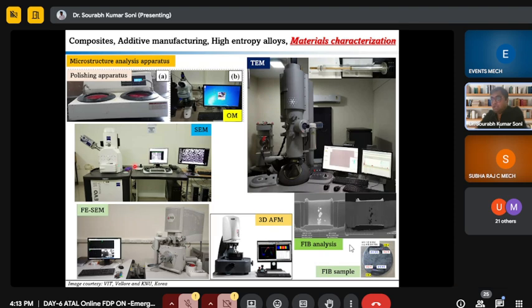This is the SEM, and this is the FESEM. What is the difference between the SEM and FESEM? I can show you in my PPT also. In SEM, we can analyze the specimen, but not with a very clear picture. So we must go for the FESEM. Why am I highlighting this? Because I went so many times to analyze my nanoparticles in SEM, but came back empty-handed because I was not able to observe the nanoparticles. So I went to the FESEM, and FESEM is very good. So you can use FESEM.